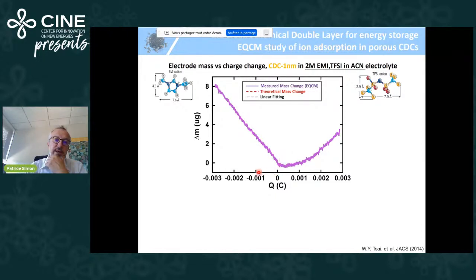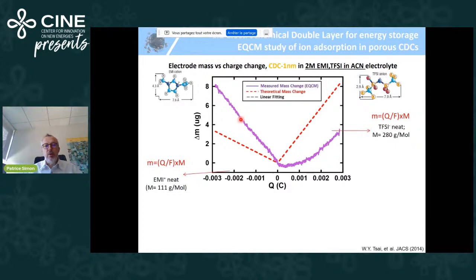So this is for negative polarization, negative charge, and this is the experimental weight change. As I told you before, the slope of delta M versus delta Q is a Faraday's law. So if you assume that when you inject negative charge into your electrode during negative polarization, these electrons on the carbon side are balanced by adsorption of neat EMI+, the molar weight is 111 gram per mole for EMI+, then you should end up with this slope. As you can see, the experimental slope is higher.